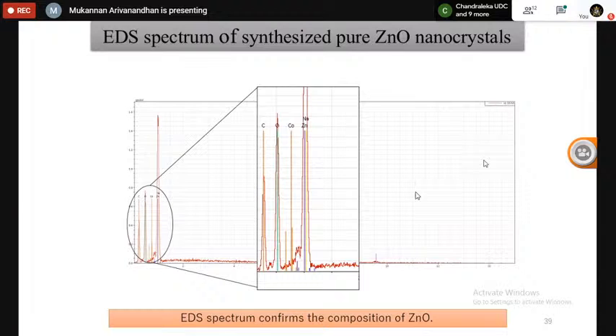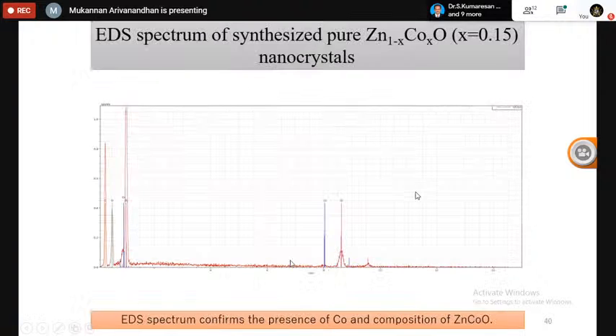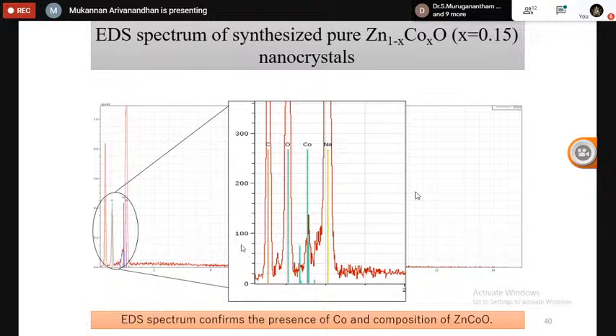Okay, and look at the pattern. This is for pure zinc oxide. There is no cobalt related peak, whereas in the cobalt substituted system, a clear peak has been obtained, which confirms the incorporation of cobalt in the zinc oxide lattice.